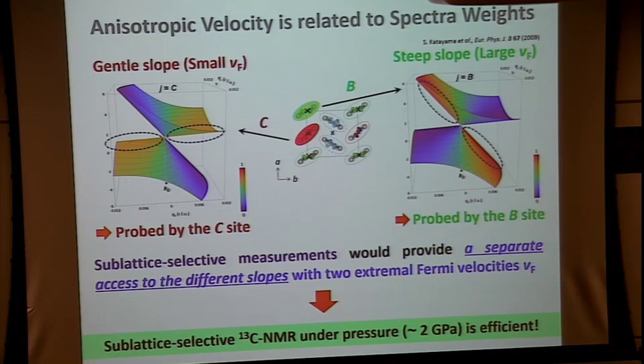And this material has very interesting electronic properties. This is the band structure calculation, the calculated Dirac cone, and this color is the amplitude of the molecular orbitals of each molecule in the Dirac cone. Now, for example, for the B molecule, this molecular orbital contributes to this steepest part of the cone. However, in the gentle part, there is no contribution. So if you know the spin susceptibility of the B molecule, you know the spin susceptibility in the steepest part. Interestingly, the C molecular orbital contributes to this gentle part. So it is the reverse, opposite situation.